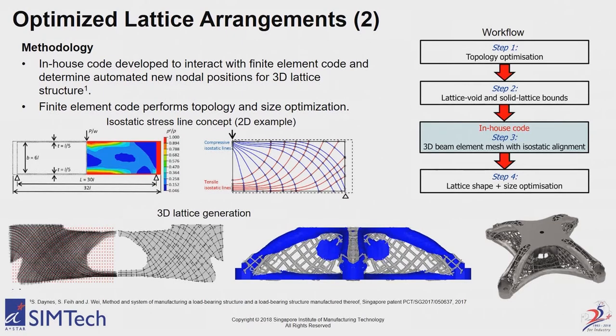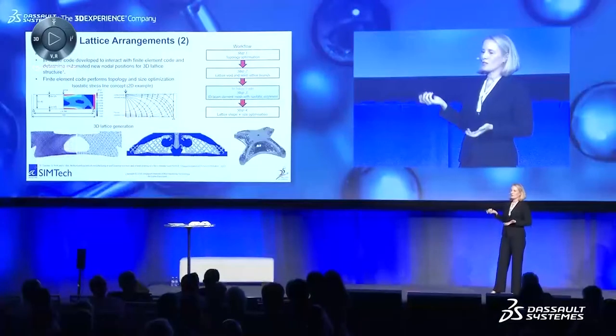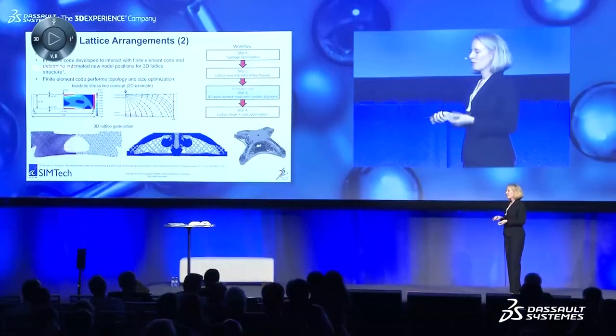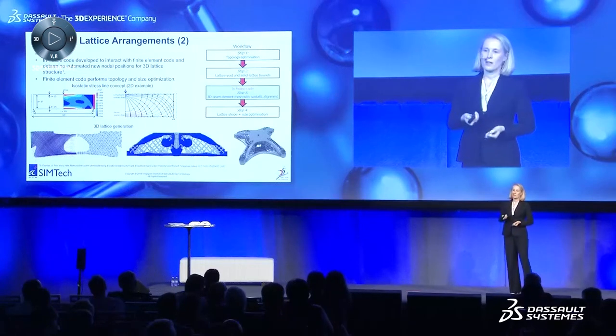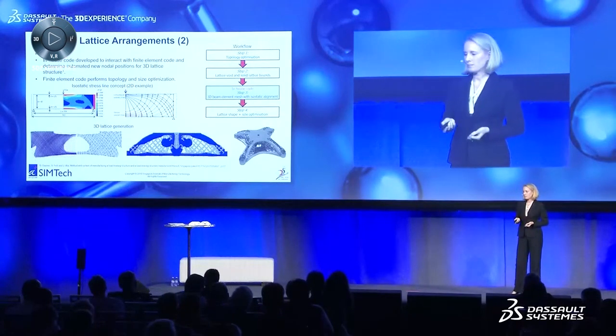One of the examples I have here is the 3D lattice. In this case, we find, very interestingly, as a side effect, that the lattices we are creating can also act as a functional support structure. So for these samples we actually need less support than for the standard topology samples if we want to print them in powder bed.